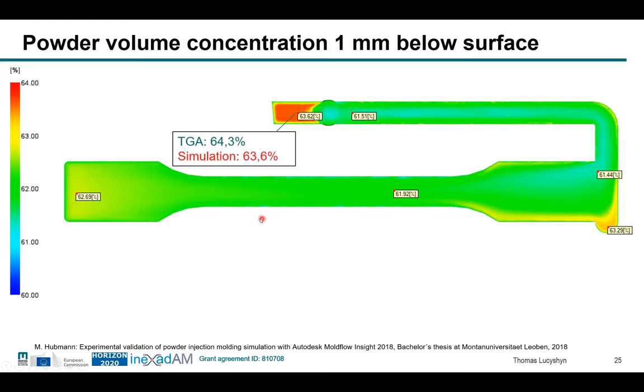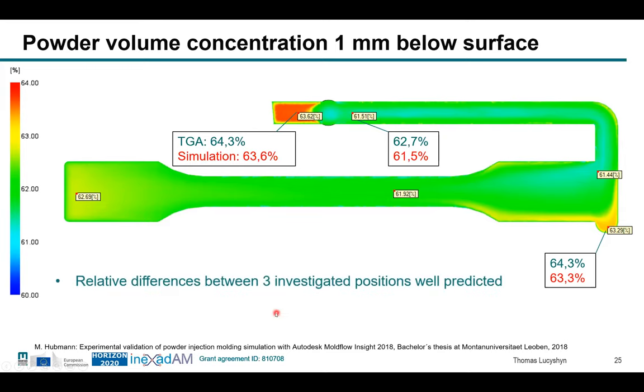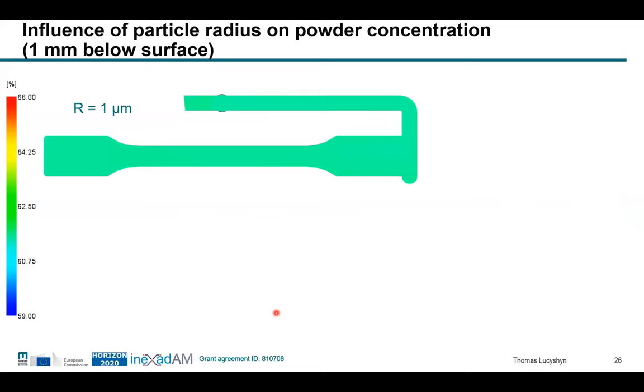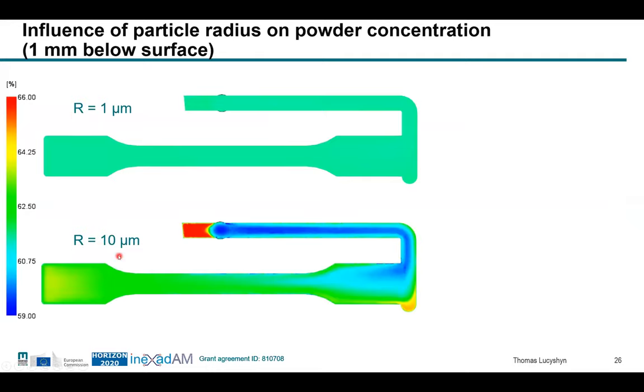We compared this with TGA measurements. So we took samples from these regions and did some TGA measurements. And we found out that although the absolute values were not really matching perfectly, the tendency was at least visible. So in this region, we had a higher value, in this region, a lower value, and in this region, a higher value again. So this relative difference between the three investigated positions was quite well predicted, but there was an underestimation of the absolute powder volume concentration. And this is closely related also to this big issue of the radius influence on the model. So we also did some additional simulations using a powder radius of 1 micrometer and one with 10 micrometers, and you see totally different results.